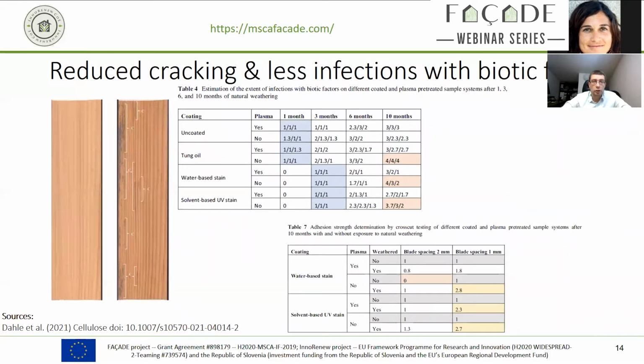A much better benefit is a reduction of cracking and, as a consequence, fewer infections with different biotic factors. On the left-hand side, you'll find a sample before and after weathering with typical infections. This is a sample after 10 months of aging, where cracks appeared on different spots, as evaluated, and we also see the shading by the biotic factors. In the evaluation in the tables, we find that this is much less the case for different kinds of coatings: tung oil, water-based stain, and also a solvent-based UV protective stain. In all these cases, both cracking and the infections were reduced by the plasma treatment during the following 10-month weathering period.